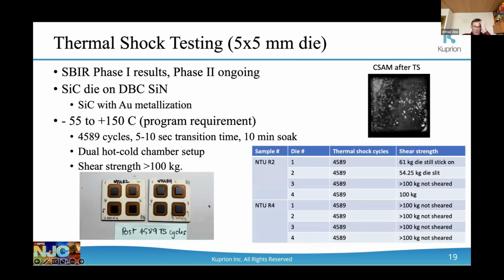Here's another one, a 5x5 on the AMB silicon nitride, simply copper islands bonded with our copper material, and these die were gold coated, I believe. In just about every case, we get bonding exceeding 100 kilos. It just doesn't shear. That's kind of the limit of our equipment. We can do this multiple times. Eventually the silicon will break.